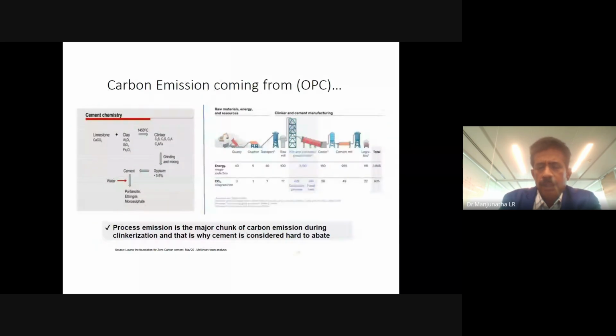So carbon emissions, as I explained earlier: to make 1 ton of clinker, almost 925 kg of CO2 is emitted. Energy consumption is close to 3,895 megajoules per ton. This is the energy requirement because the limestone goes through a process. First, we bring the limestone, we mix other additives, clay, alumina, silica, iron oxide, and have a raw meal, grind it, and heat it up to 1450 degrees centigrade with preheaters through the kiln. Then we get clinker, grind the clinker, add gypsum, and we make cement. So that's how the cement cycle works.